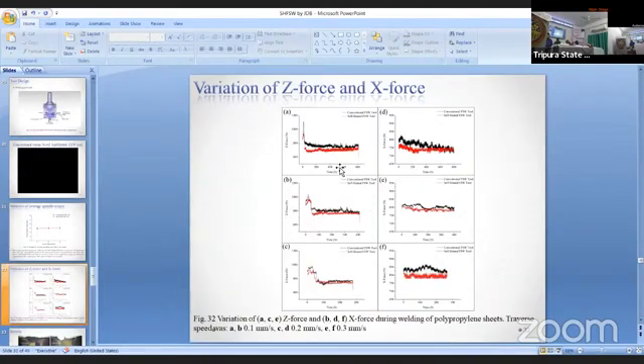And this shows the variation of the Z force and X force. So Z force is basically due to the plunging action of the tool, and X force is the resistance force that is offered by the plasticized material on the tool when it moves ahead, so in the traverse direction. So Z force, these are at different traverse speed. If we see, we can see that the Z force,